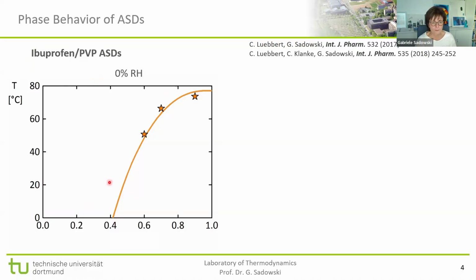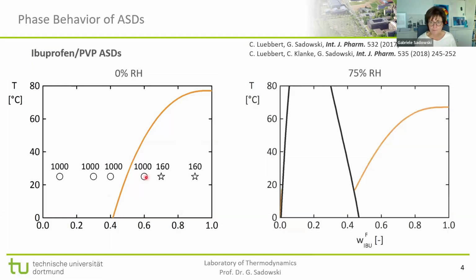that let's say at room temperature, we can have a drug load as high as 0.4, so meaning 40% of the tablet can be the API, which is very high. And so still this system would be stable, so we would not have to be afraid of crystallizing of ibuprofen in this ASD. However, if we go to higher temperatures, this changes. What you see here is our PC-SAFT calculation, that we prepared samples at 25 degrees C with different drug loads, and then we stored the samples.